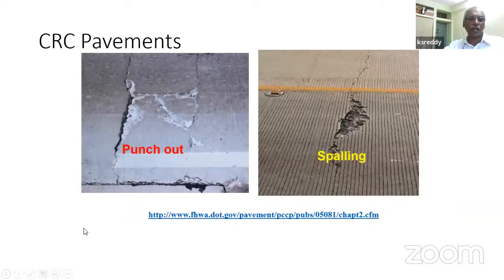This is the typical type of failure that would happen in the case of a continuously reinforced concrete pavement, because these transverse cracks, if they are too close to each other, and the maximum tensile stress would generally be produced at a location which is about 1.5 to 1.8 meters from the edge of the slab. So this piece breaks out, which is called a punch out. So when you talk about continuously reinforced concrete pavement, how many punch outs you see per mile or per kilometer is the failure criterion. So we're going to control these kinds of failure because we are going to have narrow slabs, and when you place loads on this piece it is going to break out, which is called a punch out. We're trying to control the number of punch out failures in a continuously reinforced concrete pavement. So our selection of reinforcement, thickness, grade of concrete, foundation, all this is to control how many punch outs are going to be there and how much spalling and so on.